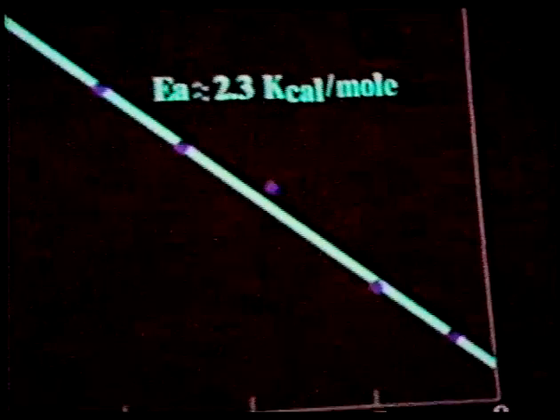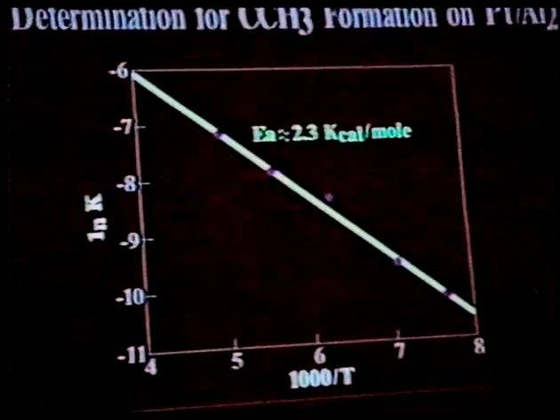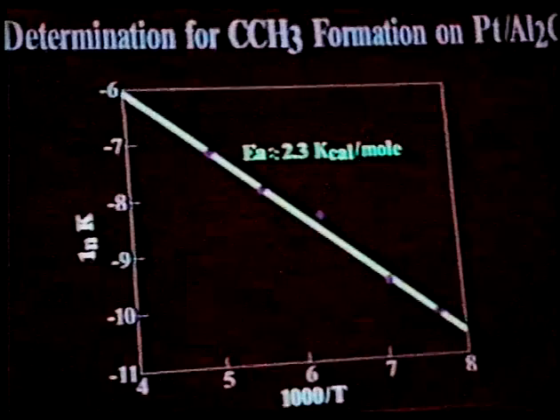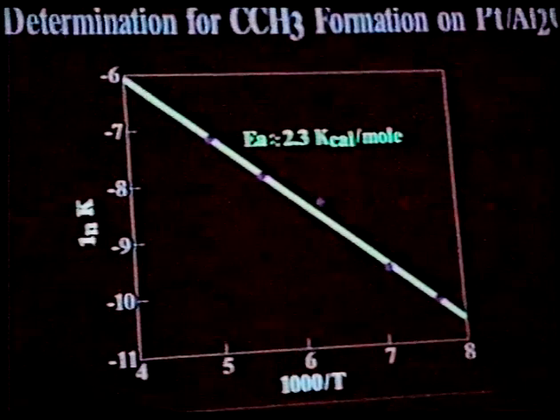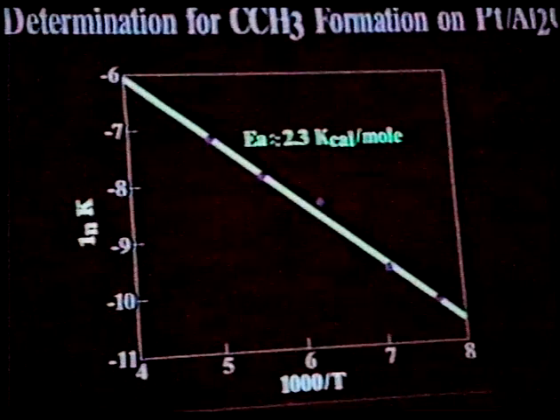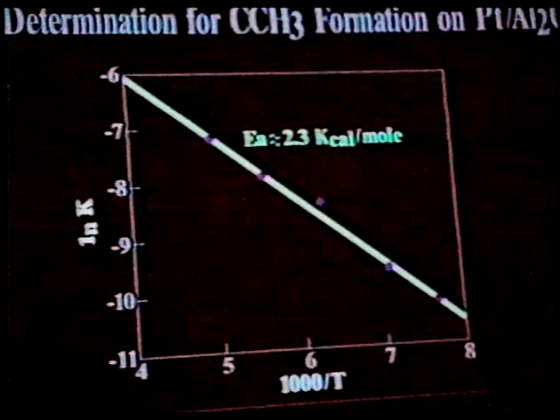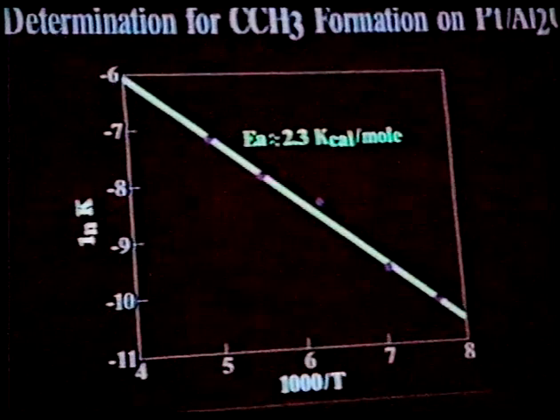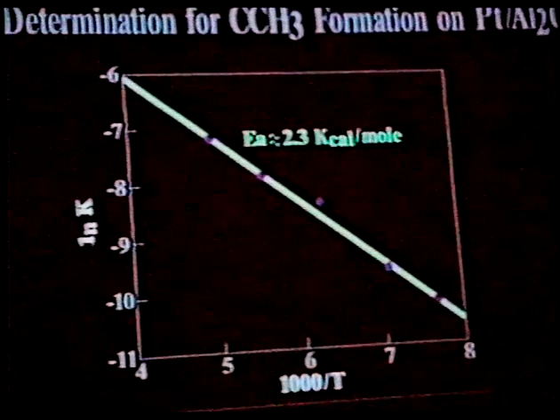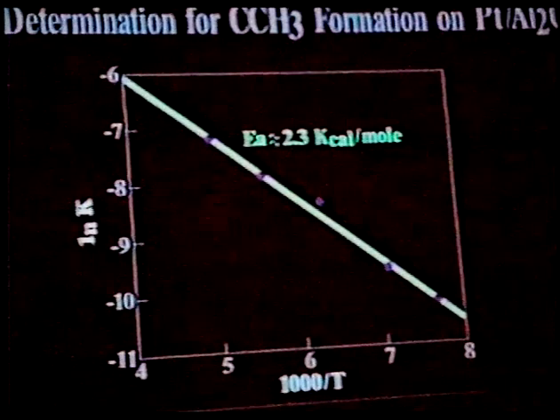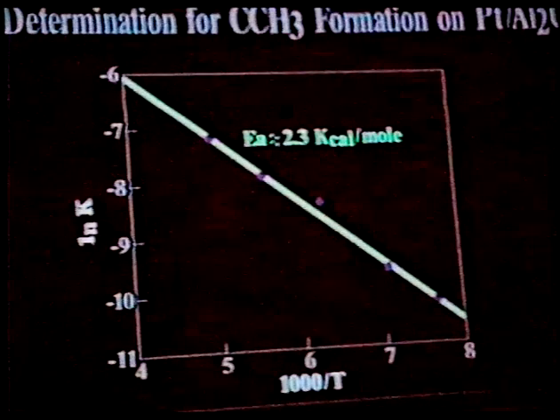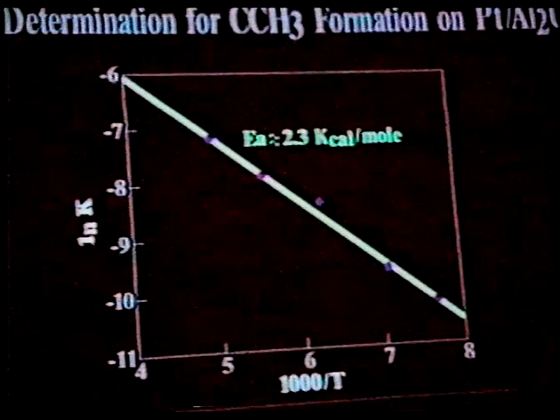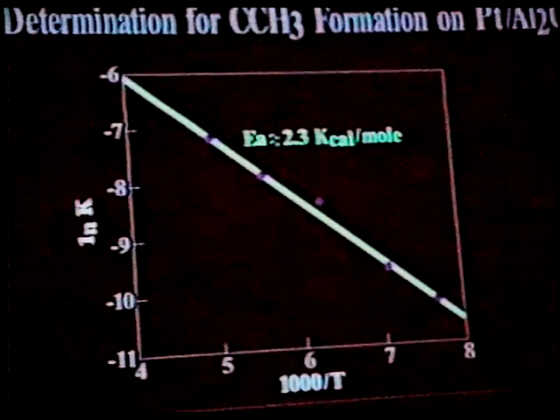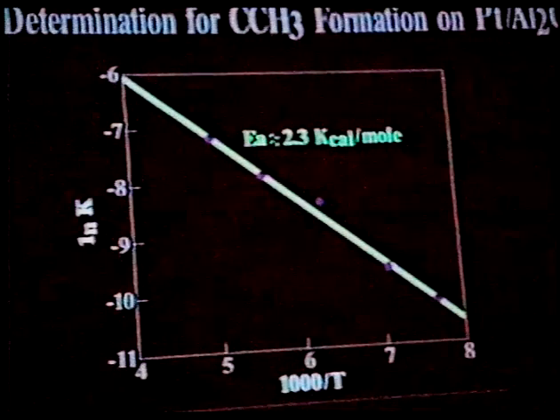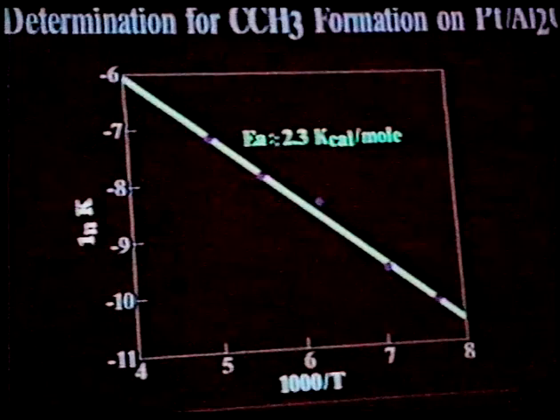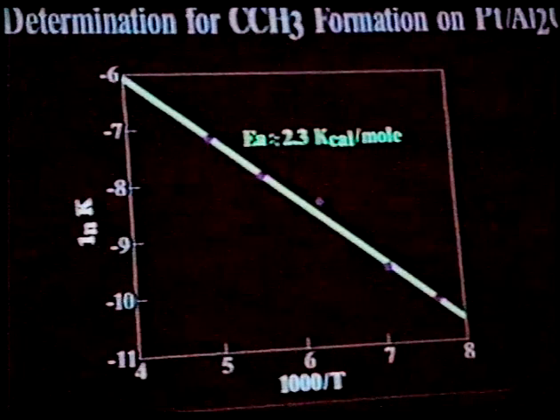Now, what I'd like to point out about this is that there have, to my knowledge, recently been up to 3 different determinations for the activation energy for ethylidyne formation on platinum 111 single crystals. And in all cases, while there is some variability in the exact numbers that one obtains, depending upon the coverage of the ethylene prior to letting it convert to ethylidyne, the numbers tend to be on the order of 10 kcals per mole, not the low number of 2.3 kcals per mole. So this appears to be some effect, whether it's a metal support effect or a particle cluster size effect, we don't know, but it's a clear indication that for this particular transformation, ethylene and ethylidyne have different energetics on a supported small platinum cluster than they do on a large single crystalline surface.